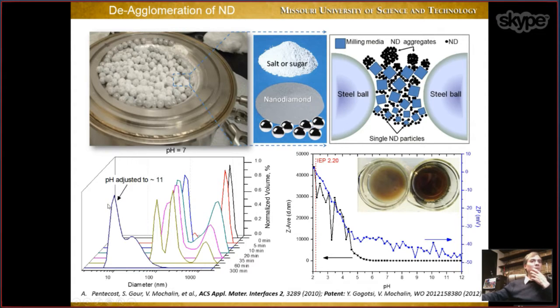You remember that nanodiamond particles are 5 nanometers in size. So our particle size distribution is peaked below 10 nanometers, at about 7 or so. So those are basically primary particles of nanodiamond. And the advantage of this technique is that we can easily dissolve salt and sugar. After milling, we simply put the material in water, salt and sugar get dissolved, we can wash it with water, and nanodiamond stays in suspension.